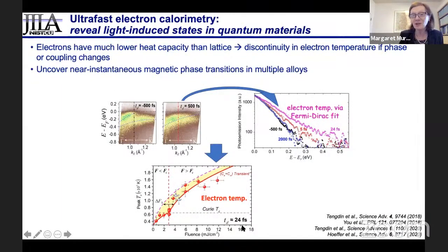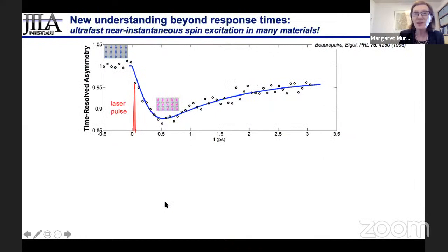by the femtosecond laser pulse, that instead of getting hotter and hotter, as you would expect if there's a constant specific heat, what we found instead was that there was a kink in the electron temperature as a function of laser fluence, and that kink had a cusp just at the Curie temperature. So essentially what this yellow region is, is the heat capacity of the spins. So essentially what we now know is